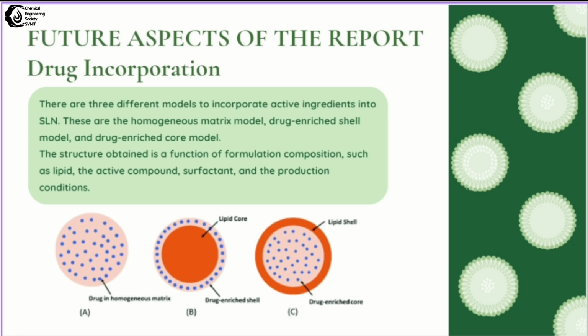The structure obtained is a function of formulation composition such as lipid, the active compound, the surfactant, and the production conditions. A drug-enriched outer shell can be obtained when the phase separation occurs during the cooling process from liquid oil droplet to the formation of solid lipid nanoparticles.